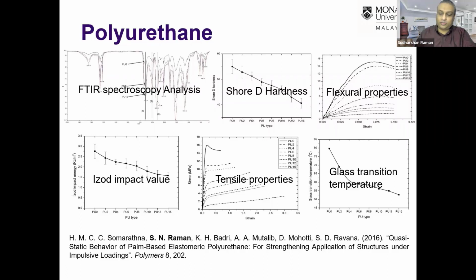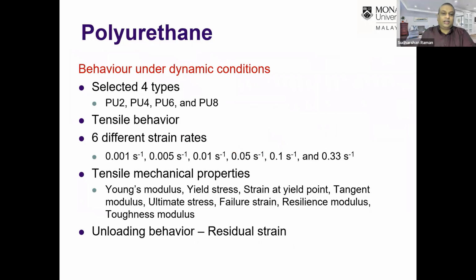So we shortlisted 4 different polyurethanes, which are PU2, PU4, PU6, and PU8, to undergo further testing under high strain rates. Okay, under the second stage of testing, we selected the 4 types of polyurethane. We subjected them to direct tensile tests at 6 different strain rates, from low strain rates to intermediate strain rates. And we evaluated the tensile mechanical properties such as Young's modulus, yield stress, strain at yield point, tangent modulus, ultimate stress, failure strain, resilience modulus, and toughness modulus. And then we also looked at their loading and unloading behavior.